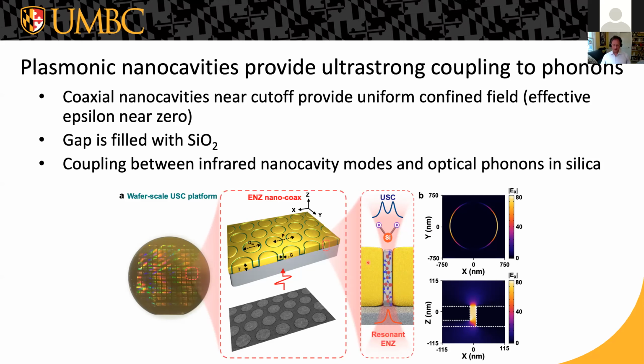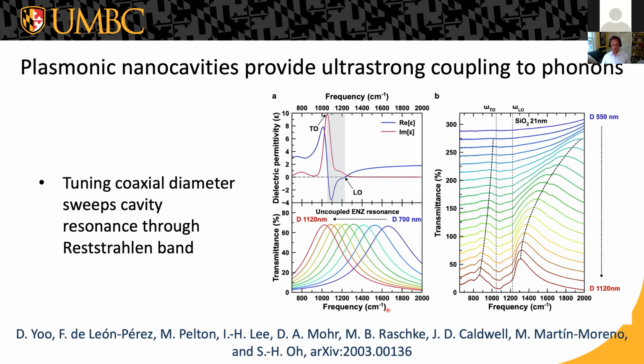So by designing cavities that have infrared resonances near these optical phonon modes, we are able to get strong coupling and ultra-strong coupling between these optical phonons and the cavity resonances. Cavity resonance frequency can be tuned simply by changing the diameters of those coaxial cavities and swept across this Reststrahlen band between the longitudinal and transverse optical phonons. And you can see that this transmission peak, as it approaches the phonon energies, splits into two peaks with a large splitting that's much larger than the width of this Reststrahlen band, which really represents ultra-strong coupling.